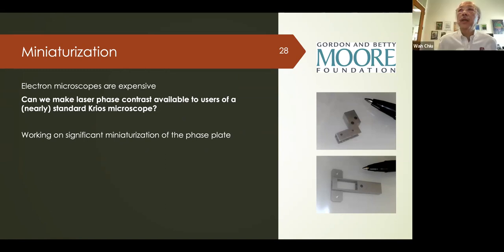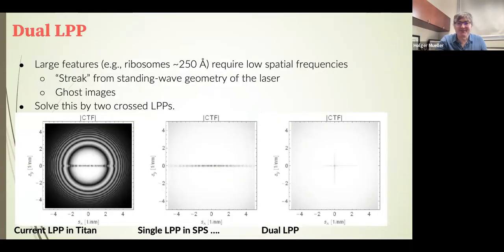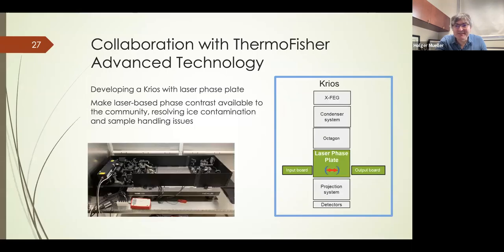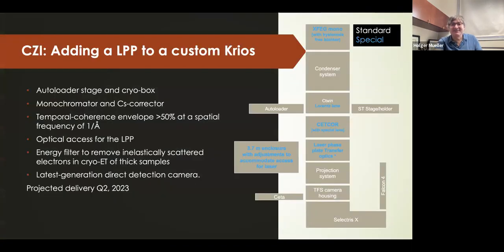Good, thanks. Another question being raised is, can we still get enough image contrast with a laser phase plate with zero defocus? Yes, this is something I wanted to keep secret. But if it was possible to reliably dial in zero defocus, and this is not at all trivial, we could talk about having a sacrificial part of the specimen which we sacrifice in order to adjust the focus and then image the rest of the specimen.